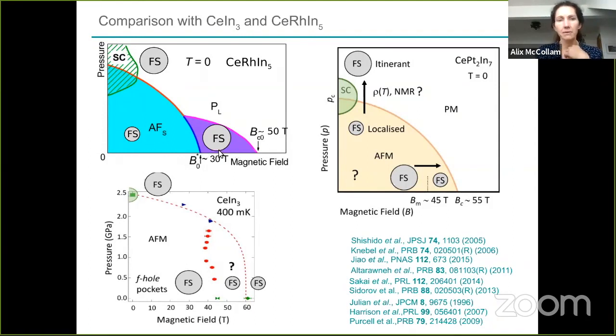In this direction, at around 30 Tesla, it's thought that there's a metamagnetic or a localization transition inside the antiferromagnetic state. So antiferromagnetic order changes a little bit to a kind of spin density wave out here. And then this is a continuous behavior of the Fermi surface, from large to still large, as you go through the actual suppression of the order at this point.